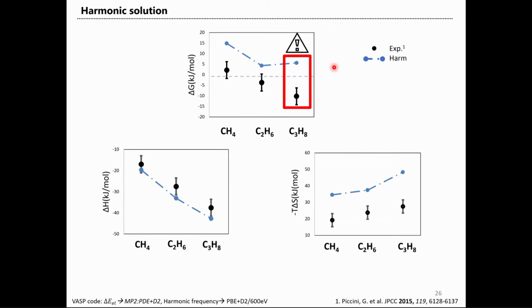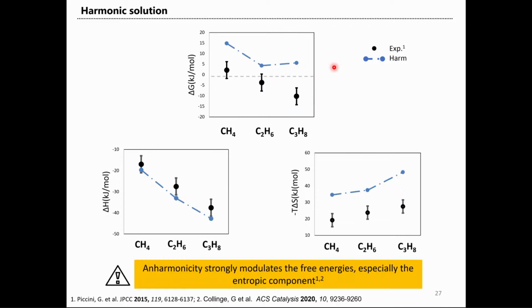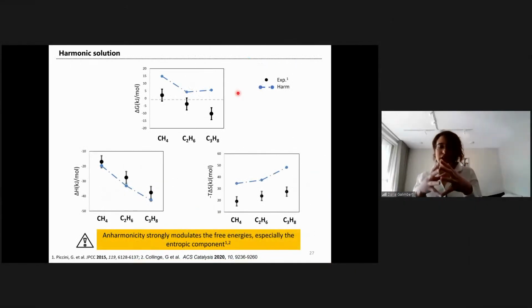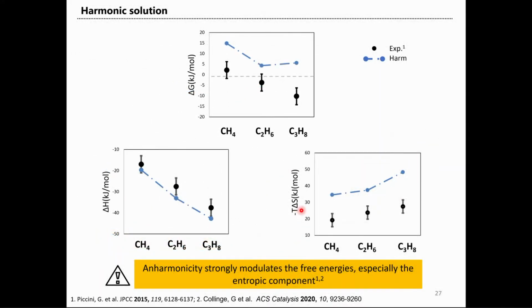And where is the problem with this approximation? The problem is that, as I told you, the entropy term depends on the full potential energy surface. And so it depends also on the portion of the potential energy surface that is not harmonic. And if we really want to have a good description of these entropic terms, we need this anharmonic contribution to be taken into account.